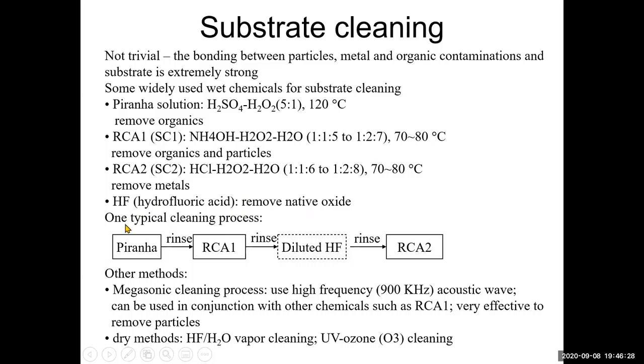And the following is a typical cleaning process. Start with a piranha cleaning, rinse. RCA1, rinse, diluted HF to remove native oxide, rinse again, and RCA2. Please know that some MEMS processes actually do not need such a high cleanness, so this cleaning process can be simplified. For example, in many cases, piranha cleaning is good enough.